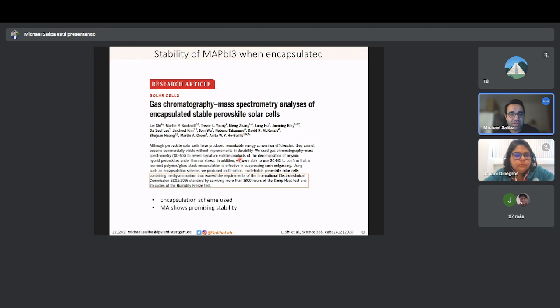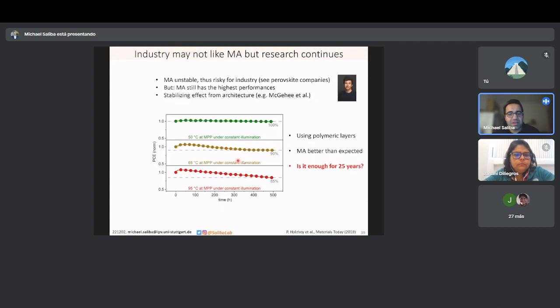And we also had a follow-up on that as well here, where using polymeric layers, so this was one of my former master students who's now at Oxford doing very well there with Henry Snaith. By using PMMA at the top, we could see that the stability of MA is improved actually. So that will be an interesting story. Whether or not it's enough for the next 25 years is something that will be investigated.